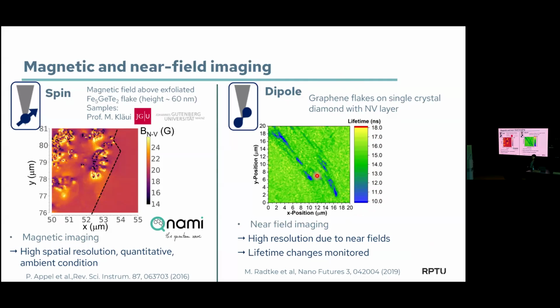We also can see the Raman signal of the graphene. So this is where the graphene is. And you see, indeed, there is a strong coupling. We have two different systems. We have the NV in the diamond and something on top. And still we can see this strong FRET here. And this motivated us to go into that a bit deeper and to see if you have really the possibility to do the multifunctional sensing. Yes?